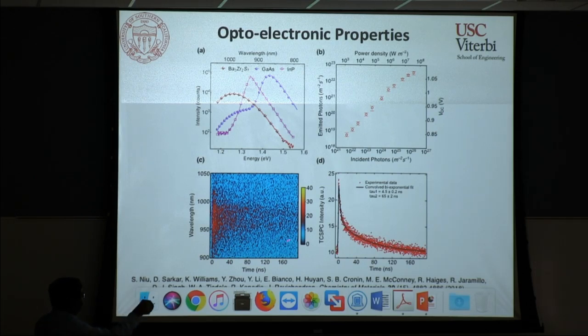The other thing that we got interested in is to try and find out what is the recombination lifetime in the system. So this is another key metric that decides whether such a material can be a good solar cell or not. If you have a long recombination lifetime, that tells you that your material is less defective, and hence it can convert the photons into electron and hole pairs efficiently.